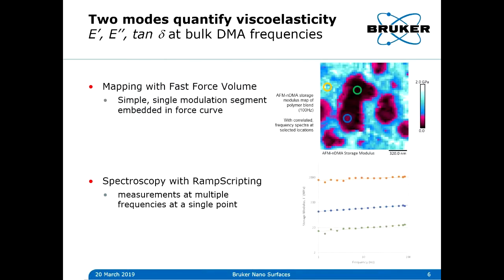So this is implemented on the icon in two different modes. Firstly, we have mapping of the storage and loss modulus or loss tangent at a single frequency. And you can see here a map of the storage modulus of a polymer blend. This is at 100 hertz, so storage modulus at 100 hertz mapped out.